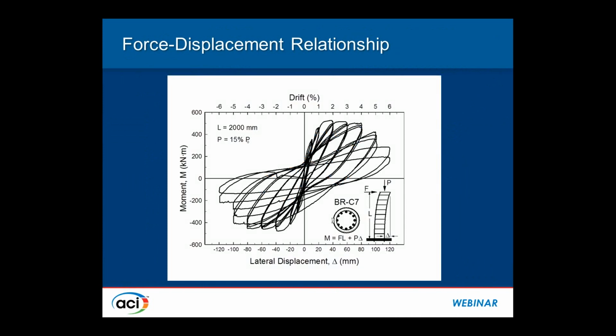Here's a typical hysteretic relationship, moment versus lateral displacement, and also indicated along the top horizontal axis as percentage drift. And obviously the slope of this line gives the stiffness. Initially there will be cracking and the elastic stiffness will start changing, and then there will be softening in the structure, and then yielding will occur. Then we'll go into the post-yield region until strength decay starts occurring and the specimen starts failing.